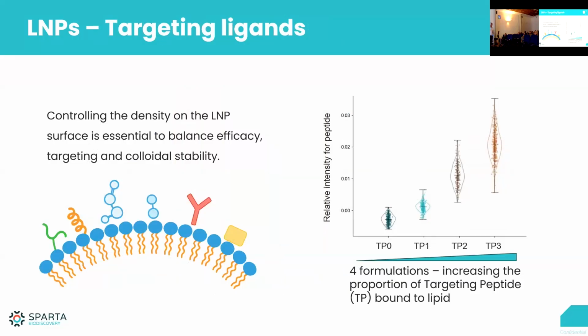And then I'll just talk to a bunch of different applications of other uses here. And you will see a lot of these kinds of plots on the right, which is univariate analysis. So basically, from these 2,000 data points that we get per particle, we narrow it down to one specific peak or one specific peak area, when we investigate different components within a particle. And the beauty of that is that we can plot these univariate plots where every dot here is still a single particle that you've measured. So you have visibility on where my particles are for the distributions, but we don't have to look at the spectra all the time. We can investigate individual components at once, because they are in principle independent in the Raman analysis.